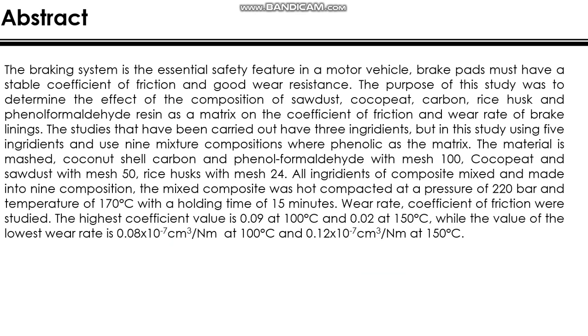The studies that have been carried out have 3 ingredients, but in this study, using 5 ingredients and 9 mixture compositions where phenolic is the matrix. The materials are coconut shell carbon and phenol formaldehyde with mesh 100, cocopeat and sawdust with mesh 50, rice husk with mesh 24. All ingredients of the composite were mixed and made into 9 compositions. The mixed composite was hot compacted at a pressure of 220 bar and temperature of 170 degrees Celsius with a holding time of 15 minutes. The wear rate and coefficient of friction were studied.